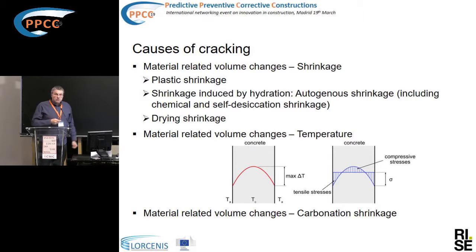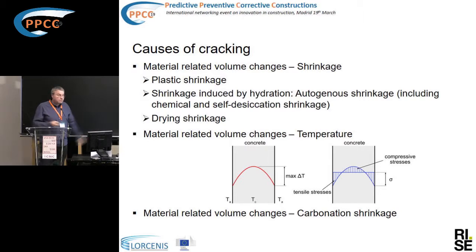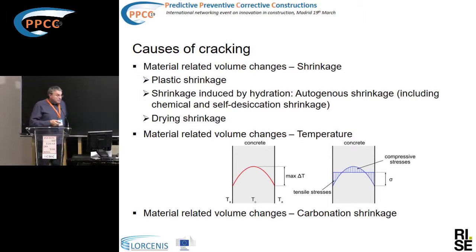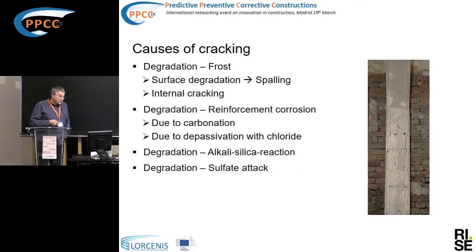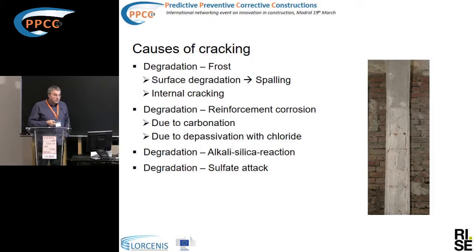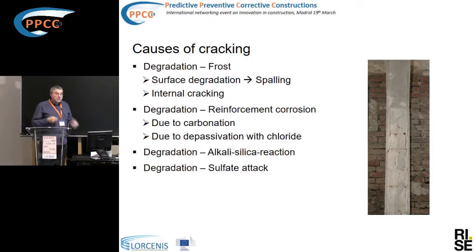There are also other volume changes, for instance carbonation shrinkage — not only calcium hydroxide carbonation but also the entire binder paste, including CSH phases and other hydration products such as AFM or ettringite. We also know frost degradation, which causes surface cracking, surface spalling, but also internal cracking.